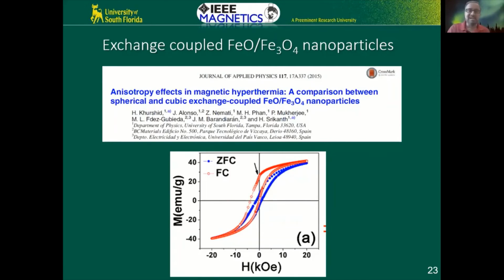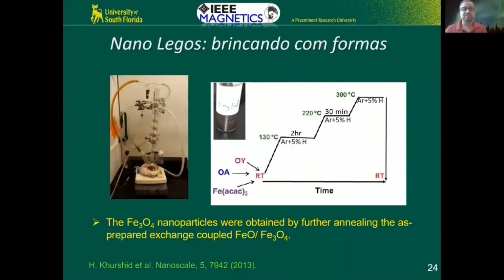And the other thing is that because it's an antiferromagnet, this is a tiny spin valve. It shows exchange bias. There's the data. We published this stuff 5 years back. You can see the loop shift when you do the exchange bias experiment by cooling the particles down from above the Néel temperature down, and looking at these curves. So these are tiny nano spin valves showing exchange bias. And guess what? This is just to show you how we can play with, yeah, okay.